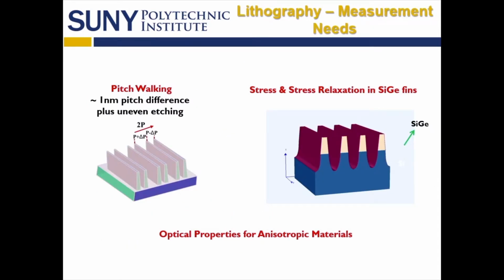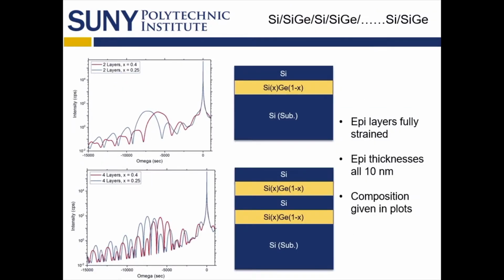All right, so now we have that same cross-section of the fins, but the top part is silicon germanium, and on the other side of the overhead, you see the pitch walk structure. Let's first look at how people often characterize this, and then we'll talk about why you would want to know it if you're looking at an AFM image or trying to do some AFM characterization. On the top, we have a single layer of silicon germanium with silicon on top. On the bottom, we have two of those.